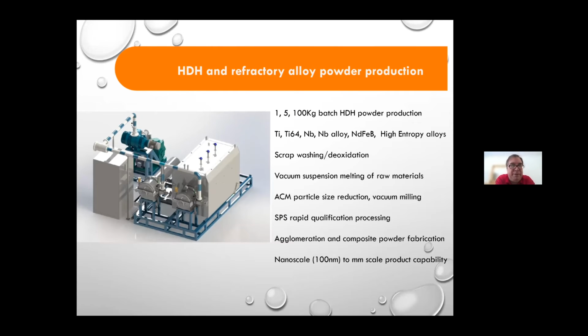Another capability that we've offered and are offering is hydride, dehydride, and refractory alloy powder production. So we have 1, 5, and 100 kilogram batch systems, and we're processing titanium alloys, niobium alloys, high entropy alloys, and magnetic materials. Includes scrap washing, deoxidation, and we also have vacuum suspension melting for custom alloys and arc melting to do both magnetic and refractory materials. We do have a pilot plant melt spinner that is coming this year as well to allow us to do rapidly solidified.